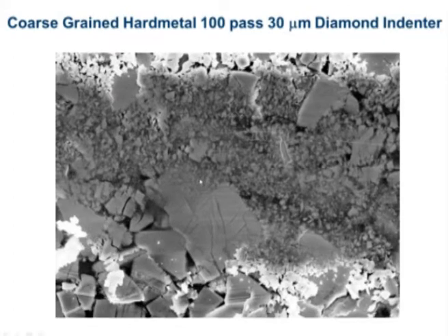So if I flick back to the other one, you can see that there's been a lot more fragmentation of the surface, and in fact a layer of this composite material, very fine scale structure, has built up, and we think this is important in terms of protecting the rest of the surface. In fact, again, you can also see some very severe plastic deformation down there.